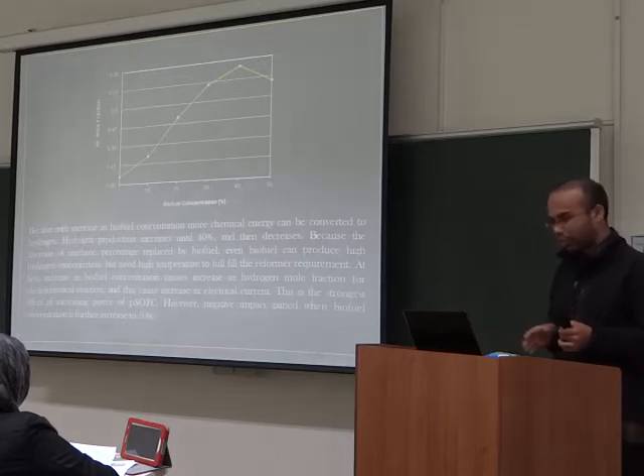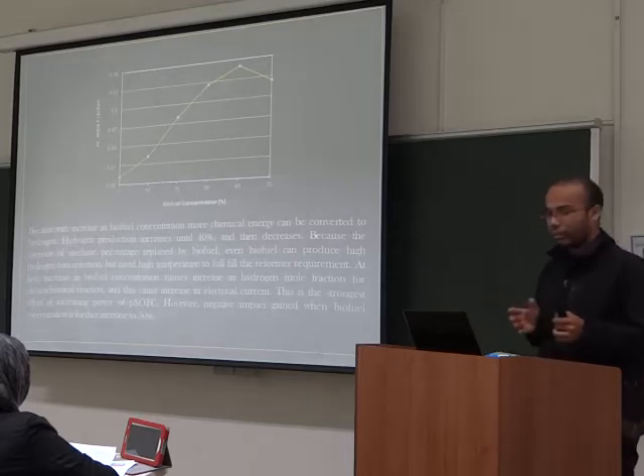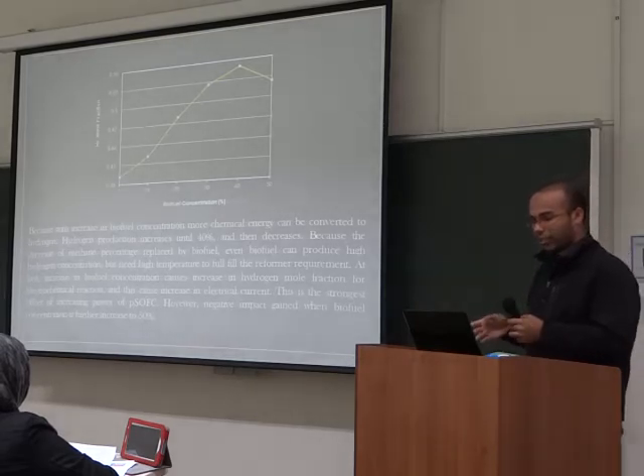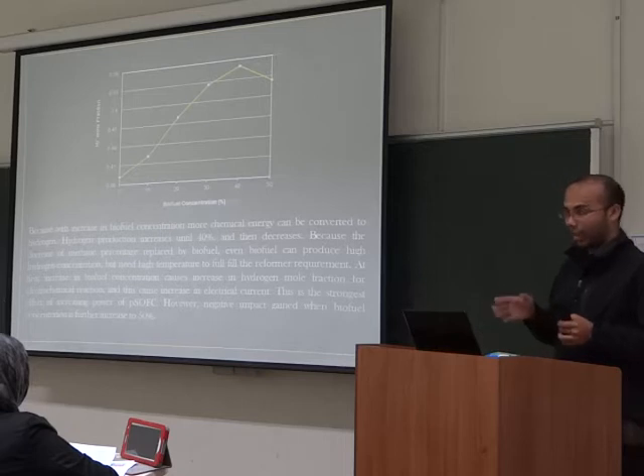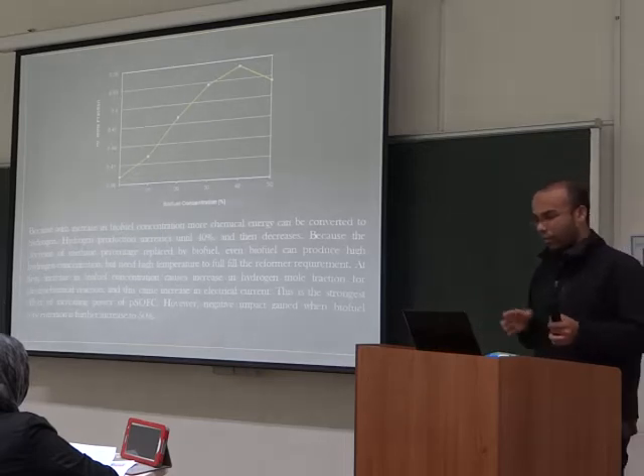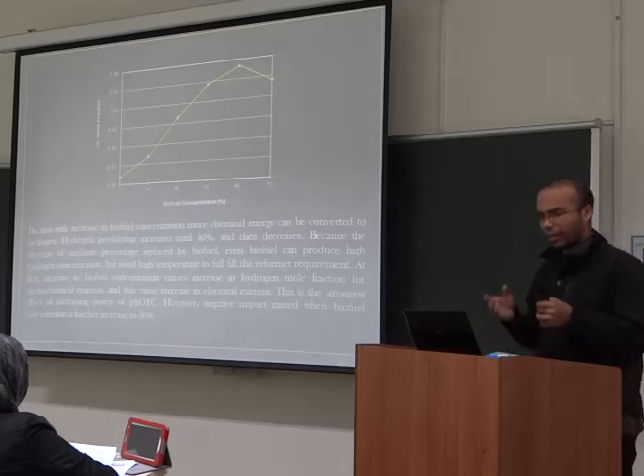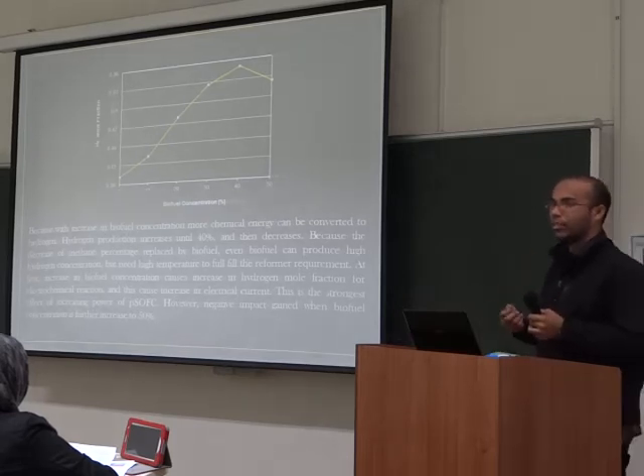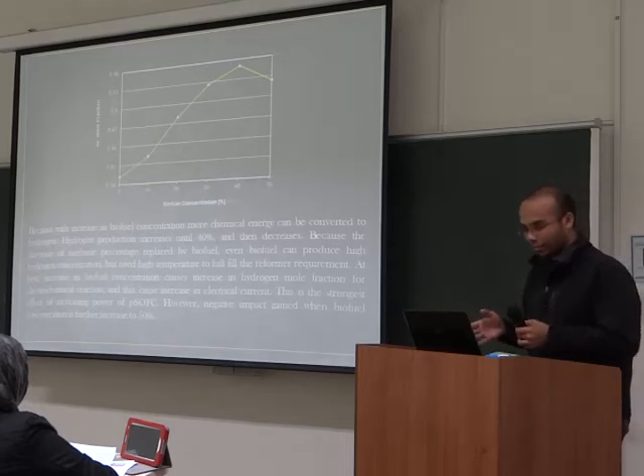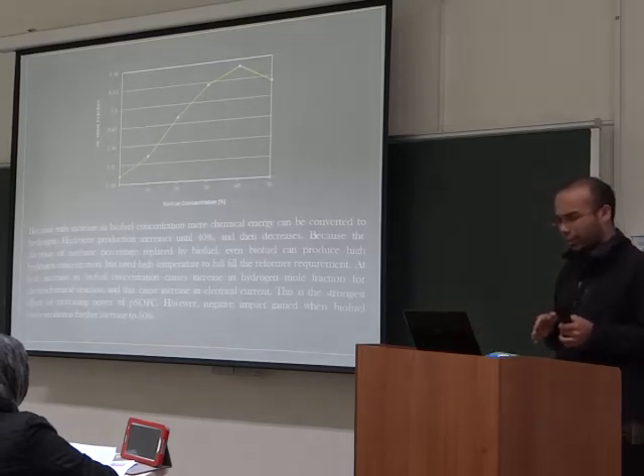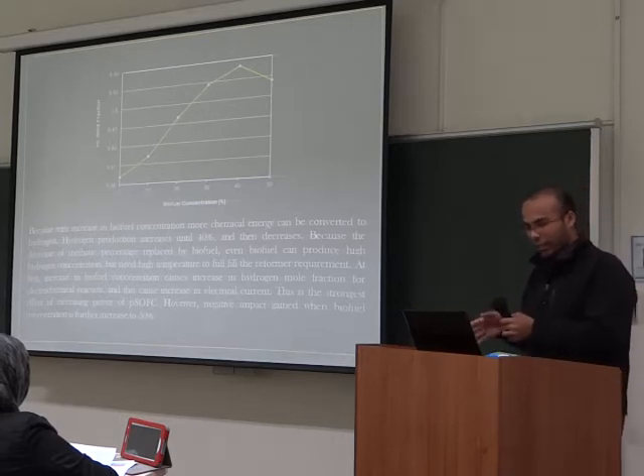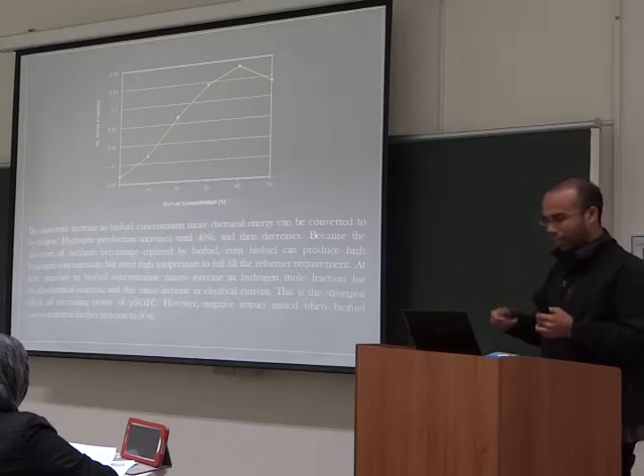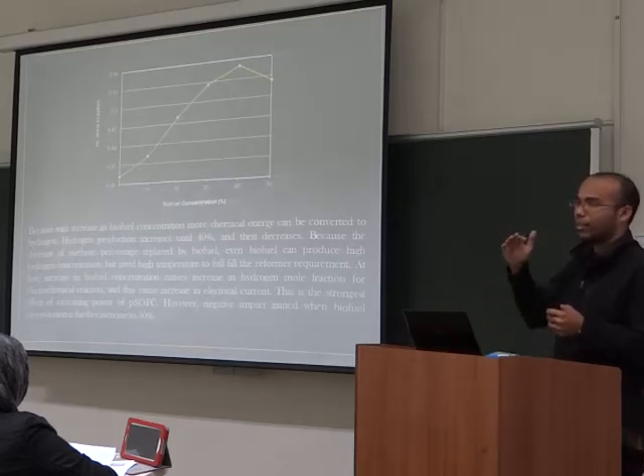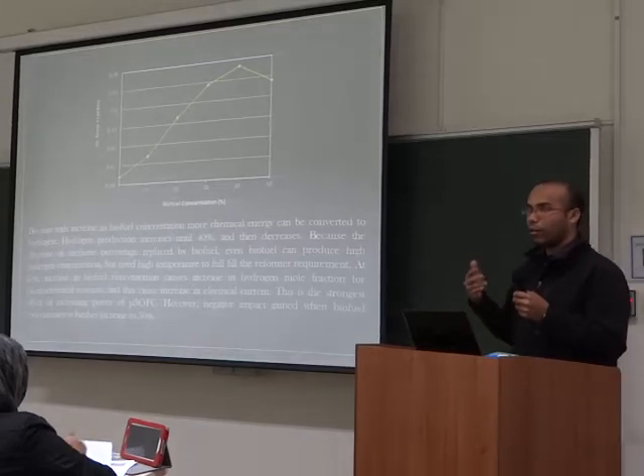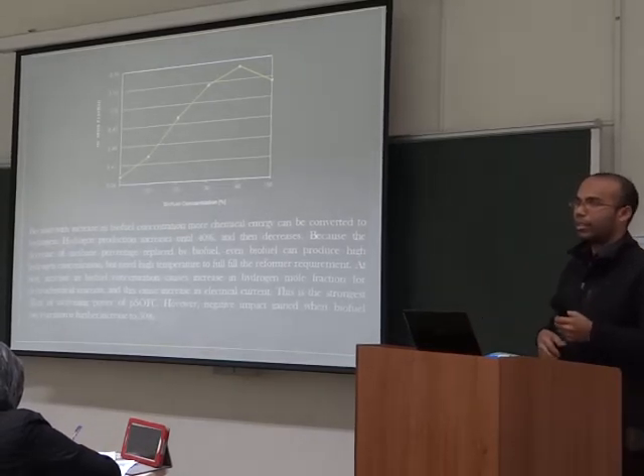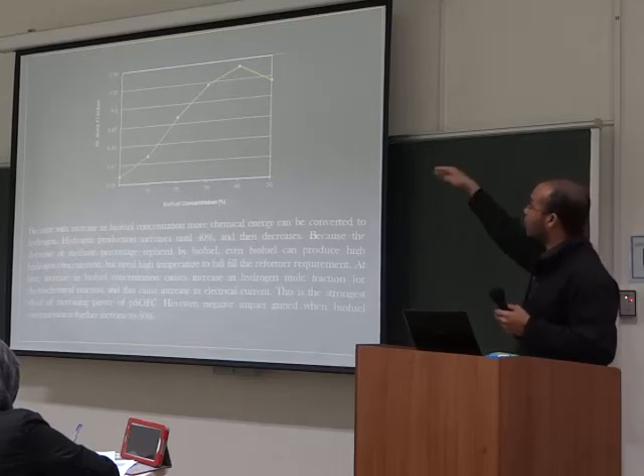Because with increasing biofuel concentration, more chemical energy can be converted to hydrogen. Hydrogen production increases up to 40% and then decreases, because the methane percentage replaced by biofuel is decreasing. Even though biofuel can produce a high hydrogen concentration, it needs a high temperature to fulfill the reformer requirement. At first, increased biofuel concentration will increase the hydrogen mole fraction, but after that it decreases because biofuel needs a high temperature for the autothermal reforming. So at intermediate temperature, the temperature is not high enough, and that's why the hydrogen production decreases.